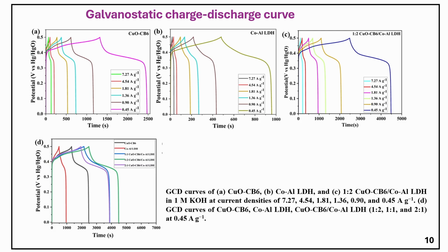Next, coming to the galvanostatic charge-discharge curve. GCD measurements were conducted to understand the pseudo-capacitance behavior of this nanocomposite. The GCD curves for cobalt aluminum LDH, CuO-CB6 and the 1:2 nanocomposite were analyzed at varying current densities. The curves for all three materials exhibited a non-linear characteristic and the specific capacitances were determined from these measurements. The 1:2 nanocomposite demonstrated a longer discharge time and superior electron transport compared to its individual components. This is attributed to the improved ion transport of CuO-CB6, which is confined within the layers of cobalt aluminum LDH.